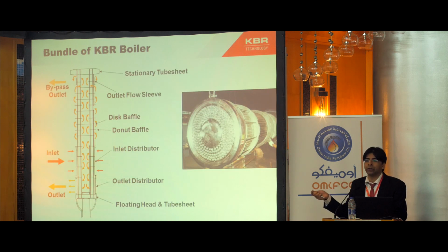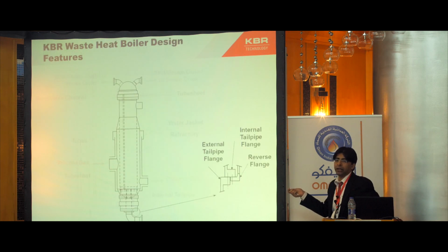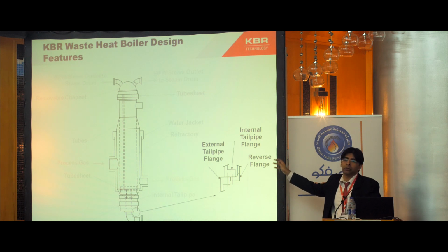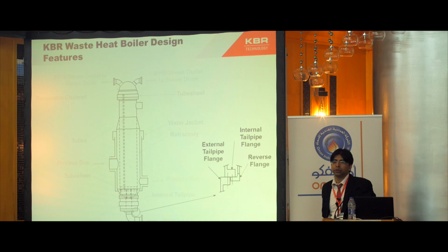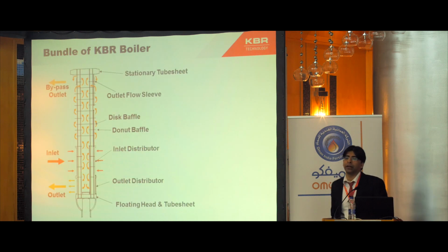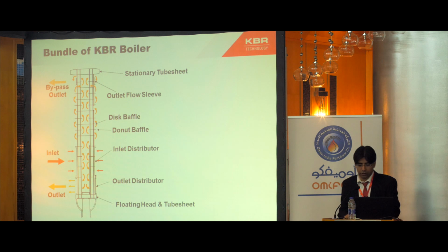Now there is no metal liner. The only thing is there is dual layer refractory, so there is no metal liner which will get out of shape. You can easily remove the bundle in 3 to 5 days. So you're keeping the water jacket around? Water jacket around, and you remove the metal shroud? Yes, only the dual layer refractory instead of metal liner. In some places with the MWK Bayonet design, we have replaced the metal liner with dual layer refractory as well. This is an in-between solution between complete replacement of the boiler with the new floating head design and using the existing bayonet design only with refractory.